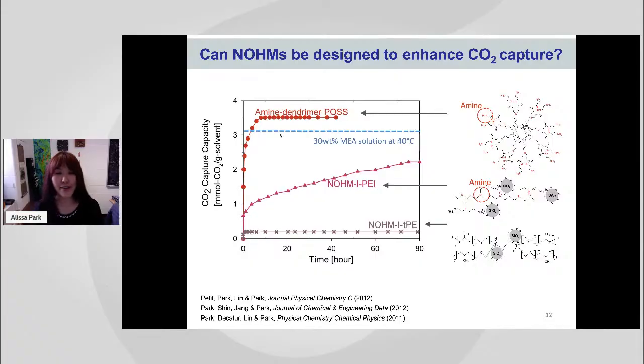And as we expected, each time we put more functional groups along the polymer chain, really doing acid-base reaction with CO2, we had a huge increase in CO2 capture capacity. This was really interesting data, and we really enjoyed the fact that, wow, this CO2 capture capacity is great. But remember the picture of the huge reactors I took at the Petra Nova site? Now we need to think about how to put that in the huge reactor at the power plant or chemical plant to actually capture CO2.